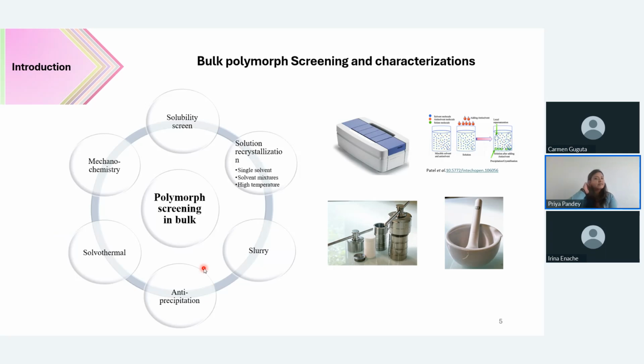When I start the bulk polymorph screening, there are several processes that we go through. The first is the solubility screening, which means that we screen the molecule with different solvents, typically ranging from 25 to 30 solvents, and screen the solvents for the concentration at which the material is getting dissolved, followed by solution crystallization. After we know which kinds of solvents it is soluble in, we can vary a lot of conditions for solution crystallization. And one of the techniques I used for solution crystallization was the Crystal16 from